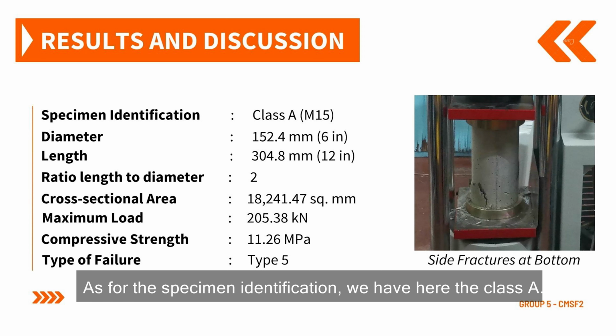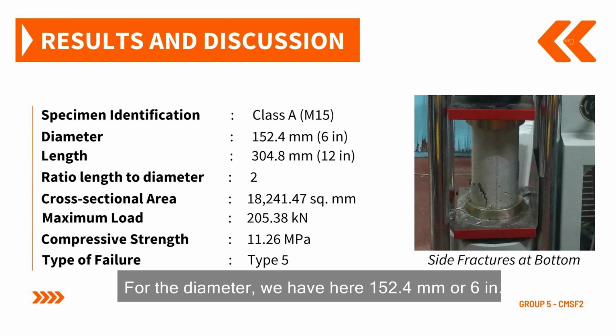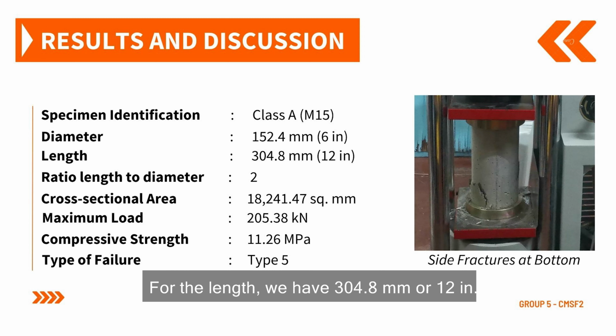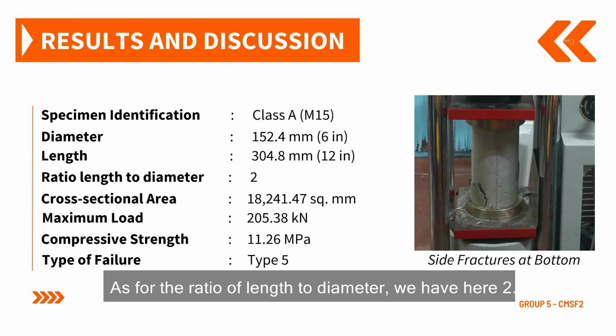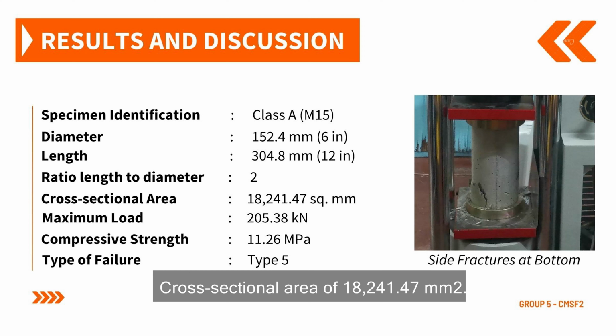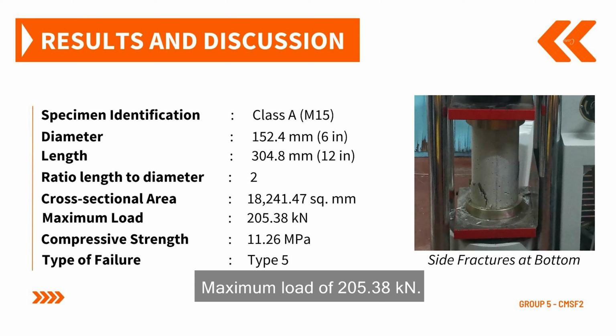As for the specimen identification, we have here the Class A. For the diameter, we have here 152.4 millimeters or 6 inch. For the length, we have 304.8 millimeters or 12 inch. As for the ratio of length to diameter, we have here 2. Cross-sectional area of 18,241.47 square millimeters. Maximum load of 205.38 kilonewtons. Compressive strength of 11.26 megapascals.